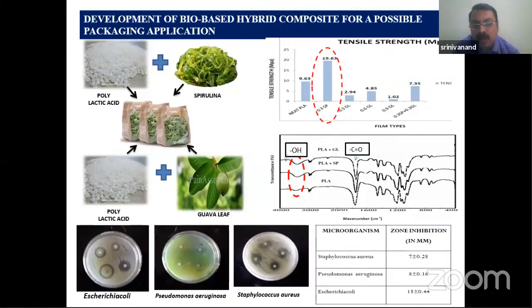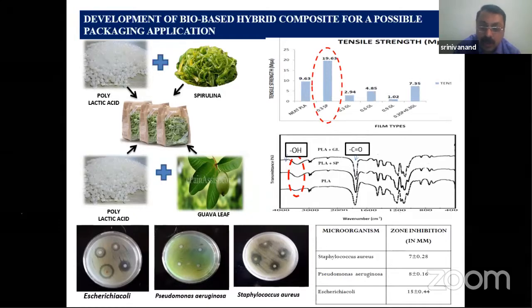And from the IR, we understood there is a good interaction between the biocide and our PLA. There is a shift in the vibration frequency, and the carbonyl peak of PLA is getting reduced when the interaction is going up. We also did antibacterial studies, and we found the combination, that is guava leaves and spirulina, was offering a very good antibacterial effect as well.